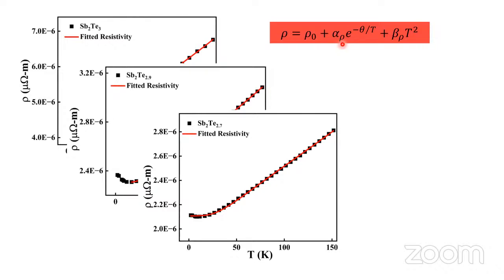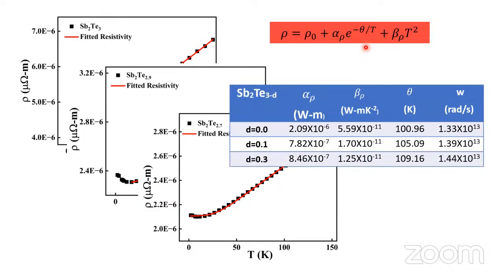Here alpha p denotes the electron phonon scattering, and beta p is electron electron scattering, and theta relates to the phonon frequency. And you can see from the table that alpha p is very much greater than beta p. That means electron phonon scattering dominates for all the systems, electron electron scattering is very low for all the systems, and you can also estimate the phonon frequency from theta, and you can see that there is a slight change in phonon frequency value for Te vacancy incorporation.